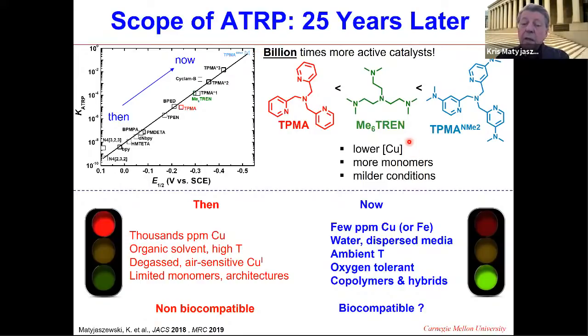Because of that, we can have a lower concentration of copper, extend the range of monomers, work under milder conditions, and in fact, not only work with copper, we can work also with iron. We can do reactions in water, in homogeneous or dispersed media. Even sub-ambient temperatures are possible. Some will be oxygen tolerant, as I will show you later today, and we can prepare various copolymers and hybrids.